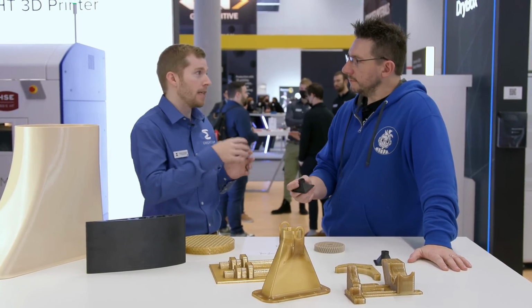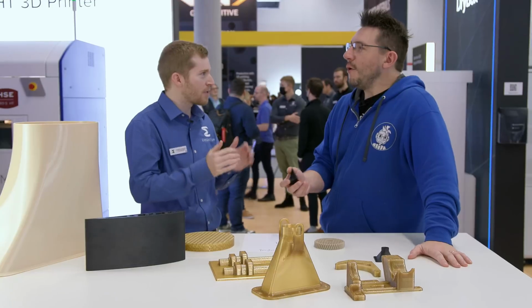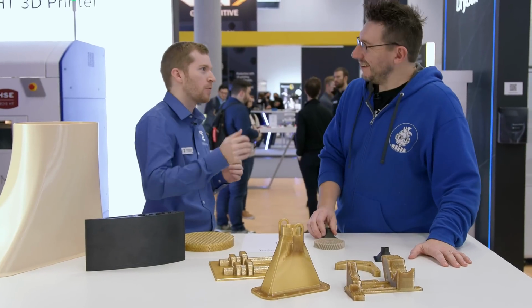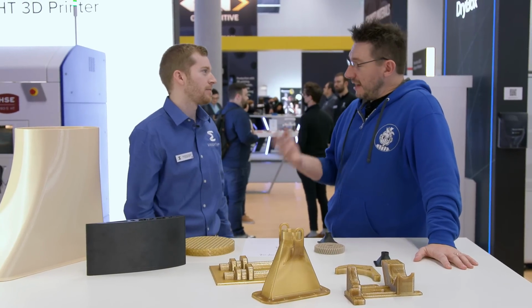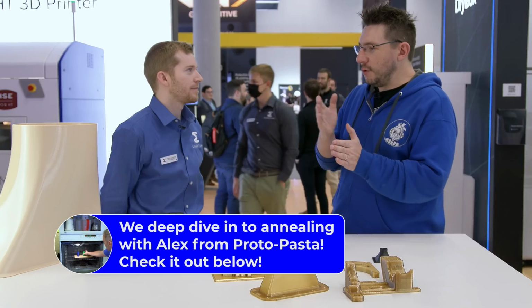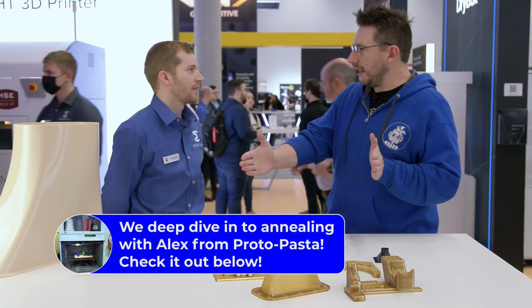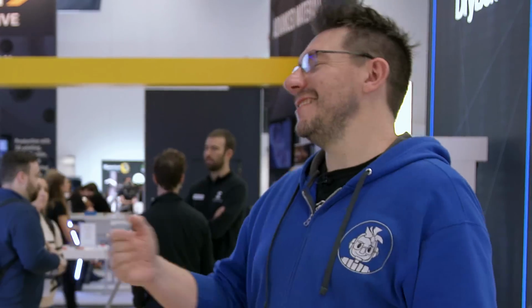And you've heard of people annealing it, right? That's right. They're heating it up in order to grow those crystals bigger and increase the amount of the crystalline regions in that polymer. It gives it better temperature performance, better chemical resistance, better overall properties in general. I've annealed PLA before, and I always thought heating it higher meant you were lining up polymer chains. That's exactly what you're doing. You're lining them up into the crystalline regions. I see.